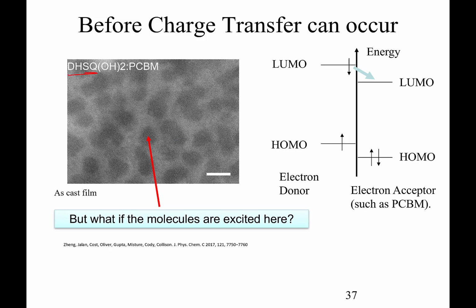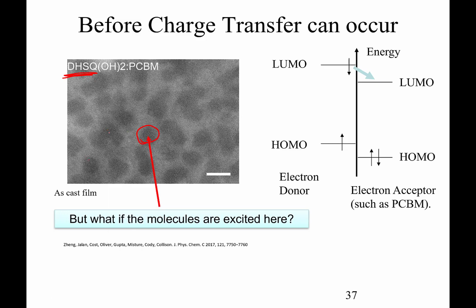this is one of the Squaraines that we've been working with, and if these domains are about, I don't know, 75 nanometers in diameter, but let's suppose that the energy can only transfer 10 nanometers, well, we've got a problem, because supposing we excite an exciton in here, the problem is that exciton has to energy transfer. It has to energy transfer to the interface between the two materials. And that can be a problem.